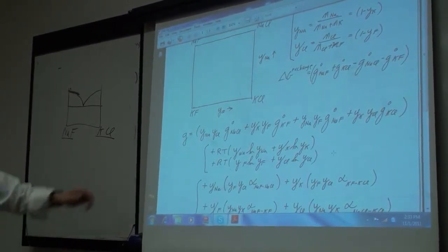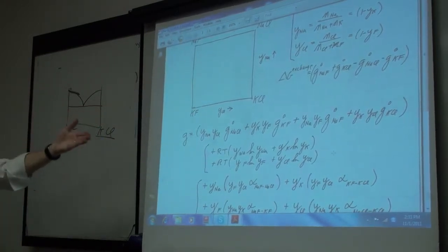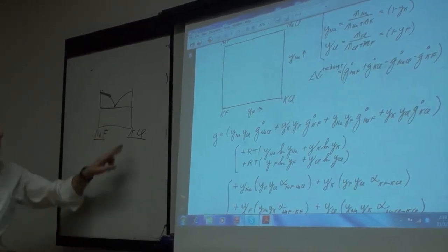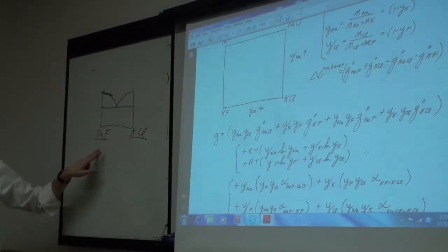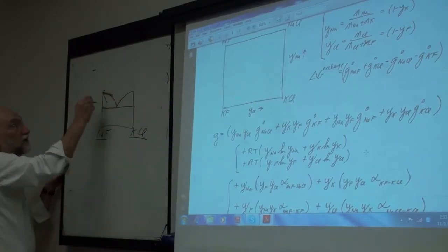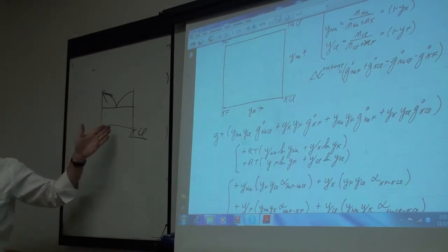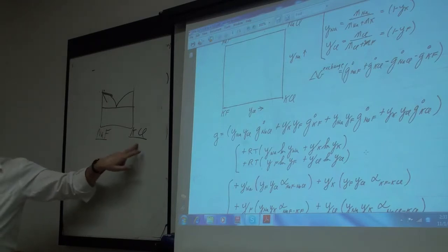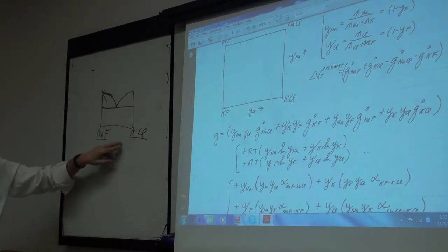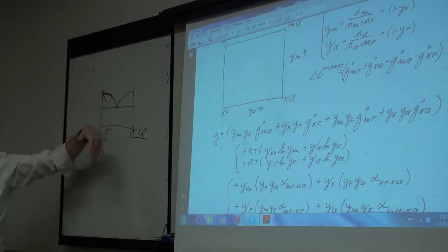So as you're going from sodium fluoride to KCl, you're not forming one ideal solution, you're forming two ideal solutions. You're getting twice the entropy. Potassium and sodium are mixing and the chlorine and fluorine are mixing. The result is, as you start off along this line, your liquidus decreases at twice the rate. You have twice the limiting slope, because you're getting twice as much entropy. If this were a molecule, you wouldn't. If this was NaF and KF or KCl molecules, you would get the slope up here, but since you're getting double the entropy, you're getting twice as much entropy as you would.